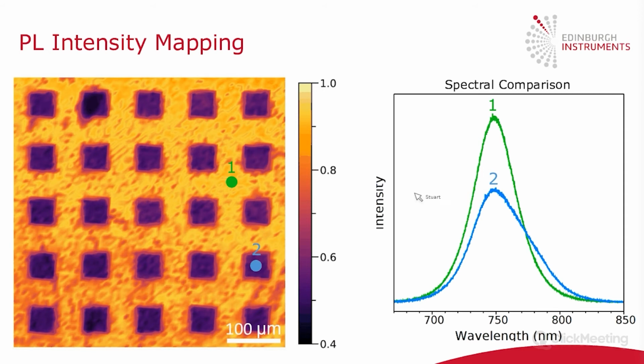And just if I show this in a spectral comparison, one thing I should make clear with all these maps is that each of these points, to make this map, corresponds to a spectrum. It's not simply intensity imaging. The intensities are post-processing. In the Ramico software of the RMS 1000, you can extract the spectra from every point in this map. So here I've extracted it at one of the bright regions, so you can see high PL intensity, and at region 2, lower PL intensity.